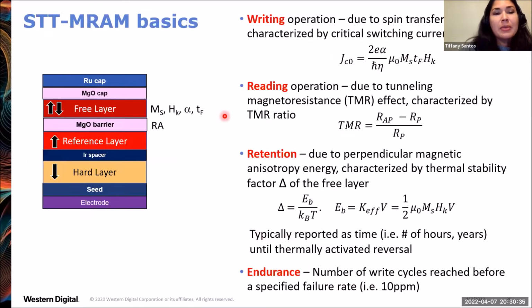Okay, so let me review some important concepts of spin transfer torque MRAM. For the writing, I showed you that this is due to spin transfer torque, and that's characterized by a critical switching current density JC0. And you can see here that this largely depends on materials parameters of the free layer: saturation magnetization, anisotropy field, the damping parameter, and the thickness. And for this reason, this is something that the materials team that I lead, we spend a lot of time tailoring these properties here for best performance.